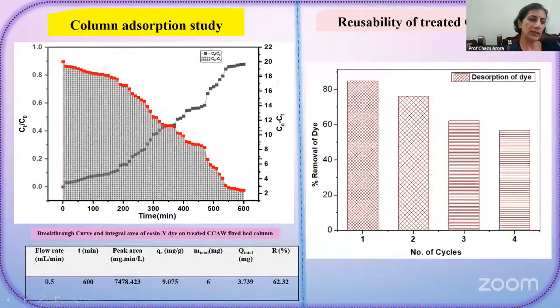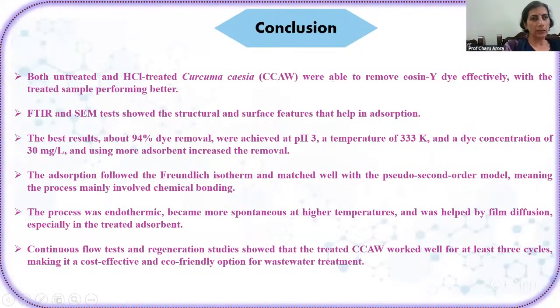These are the column studies for treated curcuma cassia waste, showing a good removal, and the material worked for 600 minutes, meaning 10 hours. It was efficiently removing the dyes. The material can be reused up to 4 cycles, showing more than 50% removal efficiency. So we can conclude that it is a very good candidate for the dye removal process, and the maximum removal can be attained at pH 3.